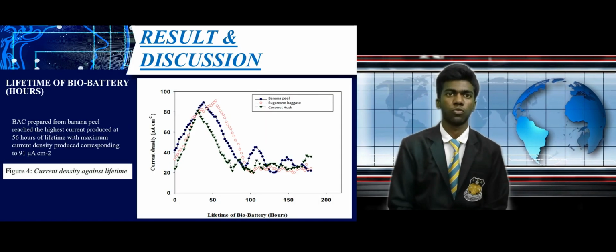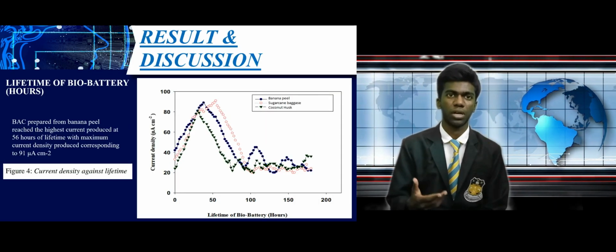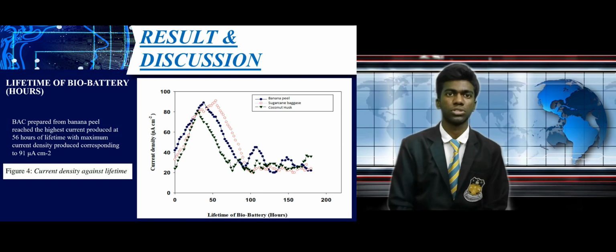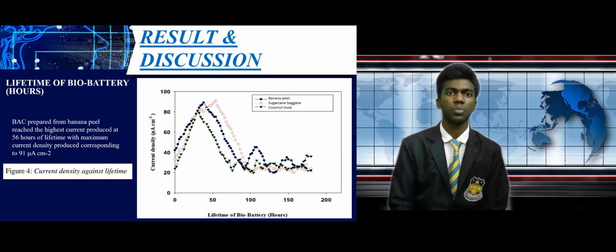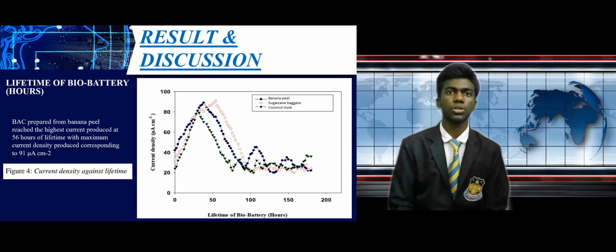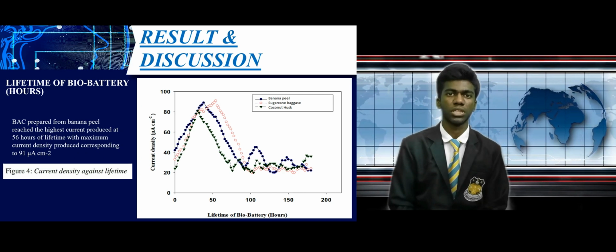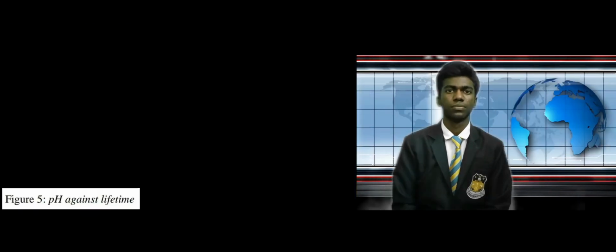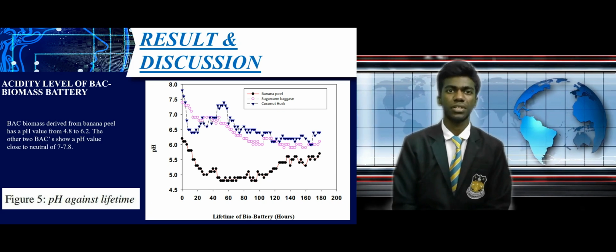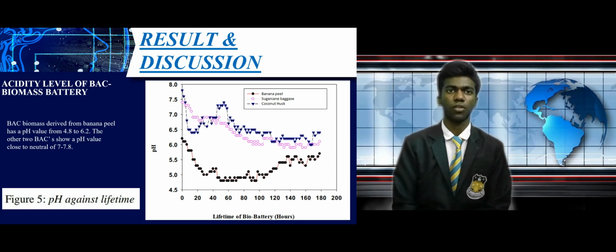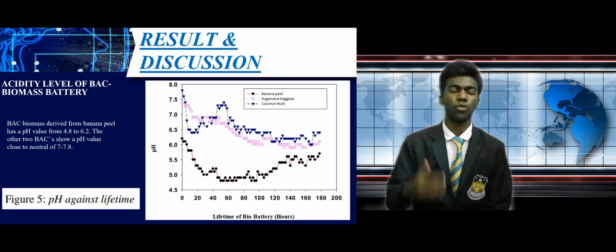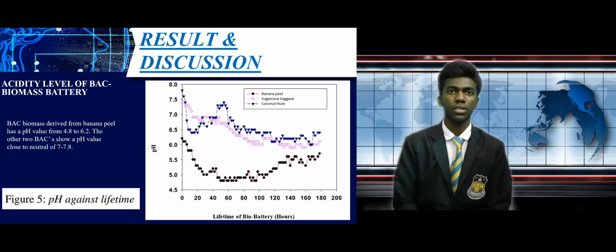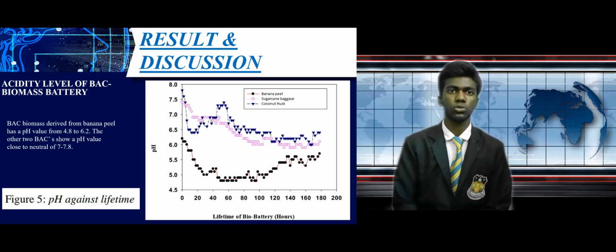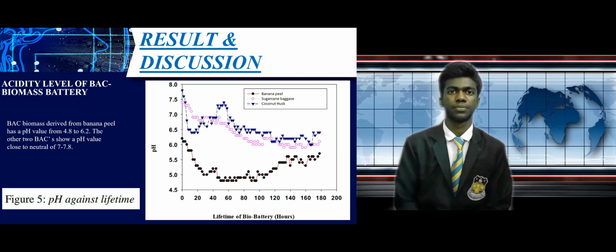Based on our lifetime of biobattery tests, BAC prepared from banana peel reached the highest current produced at 56 hours of lifetime with maximum current density produced corresponding to 91 microampere per centimeter square. Finally, the acidity level test shows that BAC biomass derived from banana peel has a pH value from 4.8 to 6.2. The other 2 BACs show a pH value close to neutral of 7 to 7.8.